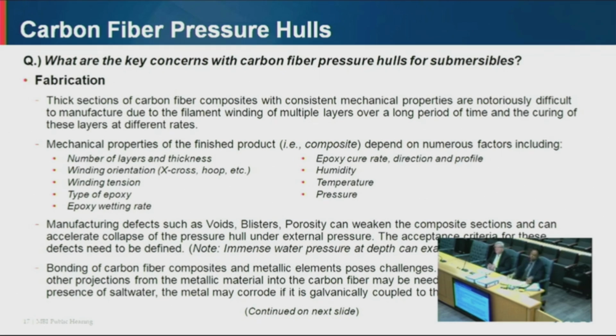If you don't properly cure it, the mechanical properties can be degraded. So pressure is another important consideration when you cure your carbon fiber composite. The composite can be cured at 1 atmosphere in a standard oven, or it can be cured under pressure in an autoclave. An autoclave is basically a pressurized oven. The pressure will drive out the air pockets in the carbon fiber composite and will compress it. So you get a better product if you cure your carbon fiber composites in an autoclave versus curing it in a 1 atmosphere oven.